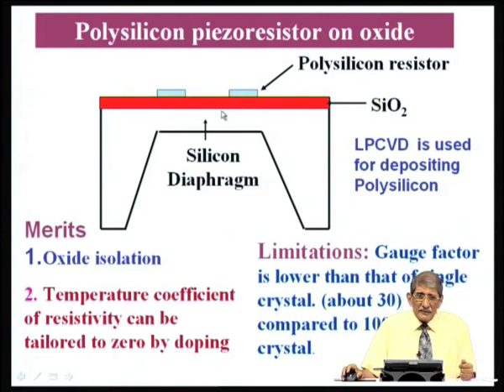So, you can use this type of resistors in the form of a bridge and make use of this for realizing pressure sensor, which can operate at temperatures like 300 to 500 degrees centigrade very comfortably. Okay. As we have seen, you get oxide isolation here, temperature coefficient of resistivity can be tailored to 0 by adjusting the doping, just now we have seen. Okay. Now, but you can't get anything free, you have to pay for these benefits by something. That is, limitation is that gauge factor is lower than that of single crystal.